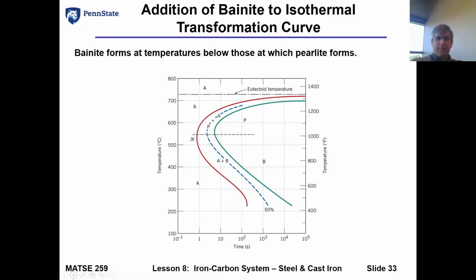And by the time we're at 10 seconds, we are really a completely bainitic structure. So we see just from 625 to 500 degrees C, how we go from a fine pearlite structure to a bainitic structure with just 125 degrees C difference in temperature. The times are almost equivalent to form completely different microstructures, completely different properties, with that change.